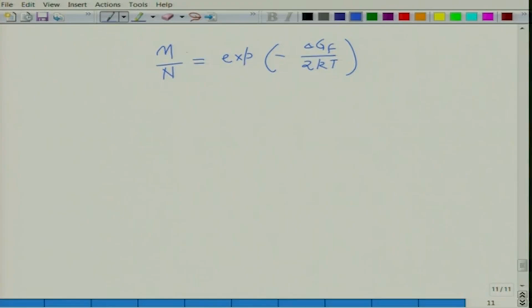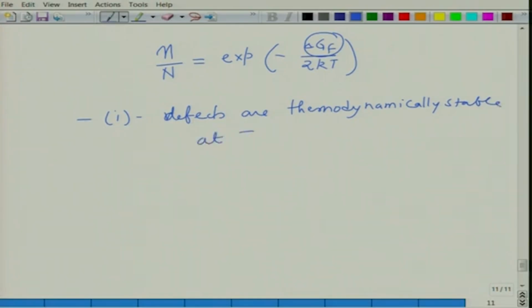So this is what it works out to, that there is an equilibrium vacancy concentration which is proportional to exponential of minus delta Gf. So basically what it says is that, one, defects are thermodynamically stable at T greater than 0 Kelvin. So as long as temperature is more than 0 Kelvin, they are stable. Two, as defect formation energy goes up, the small n will decrease, which means the stronger the defect, the more energy you require to form the defects, the lower the number is, which makes sense.